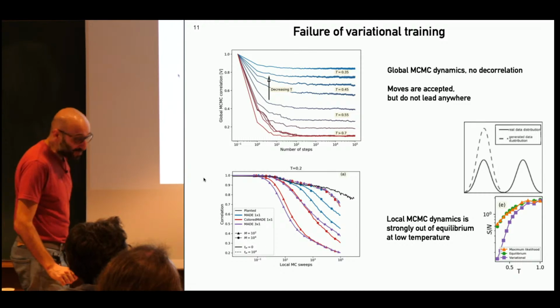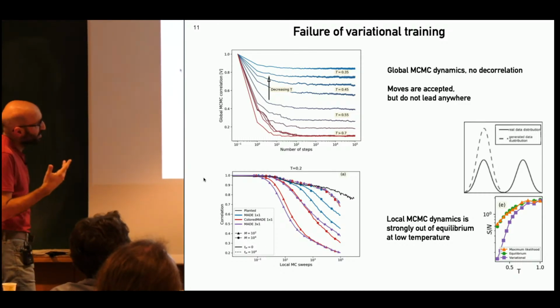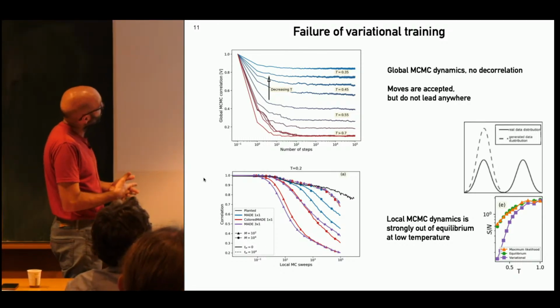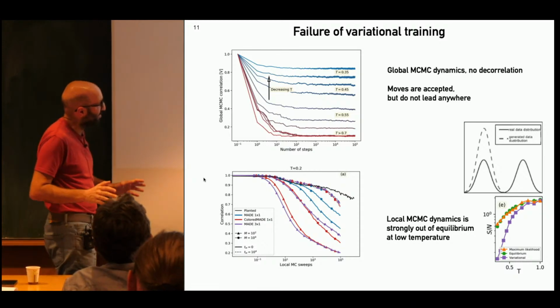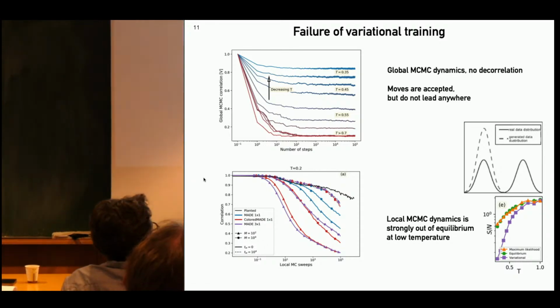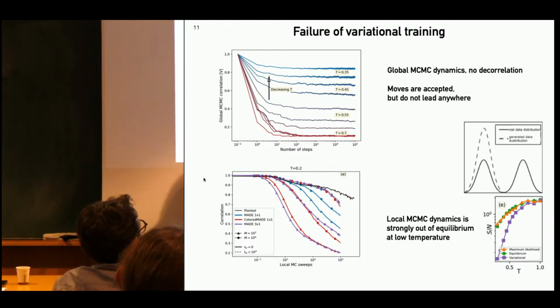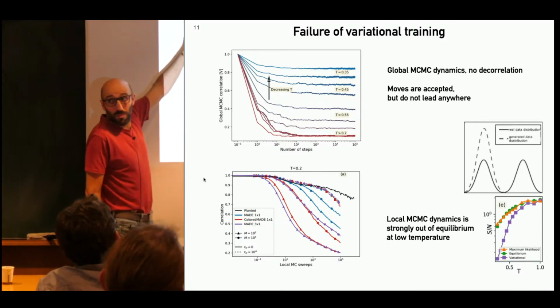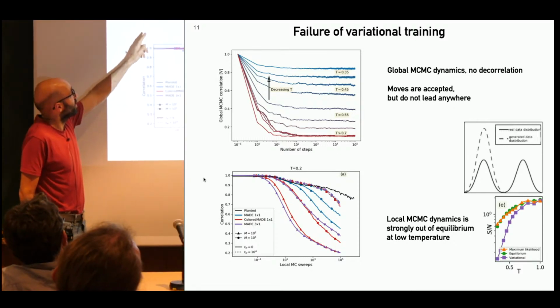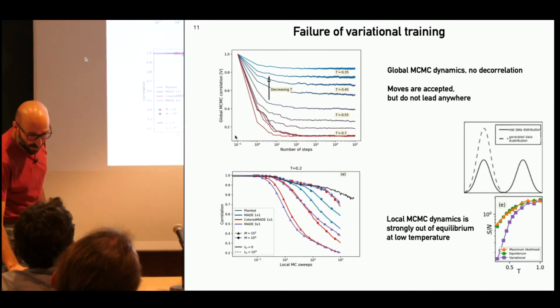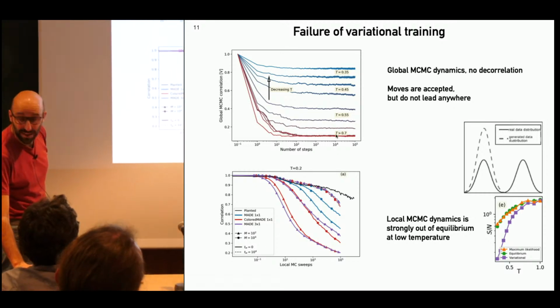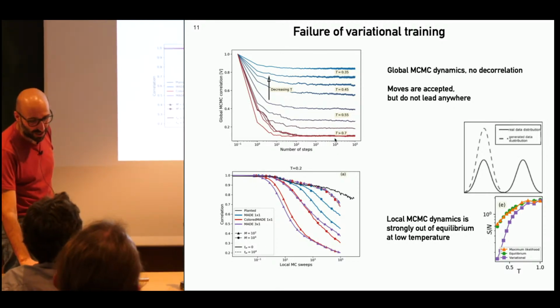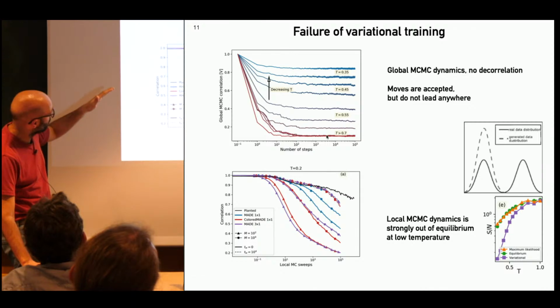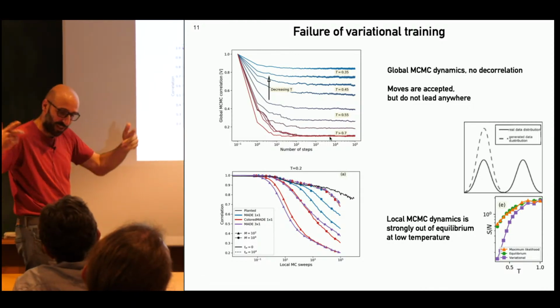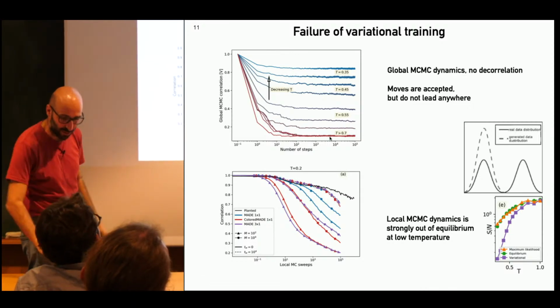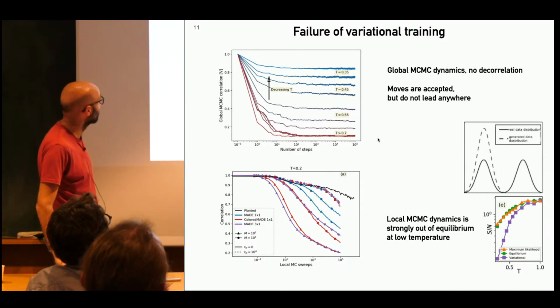I'm going to finish. So what's the problem we found? The variational model is mode collapsing. And this, I think, at this point is quite clear. The entropy is going down. And also, if you run global MCMC using the variational model, what you see is that at some point the correlation doesn't go to 0 anymore. It should go to 0.1, because you have 10 colors. So if you take random configurations, the correlation is 1/10.